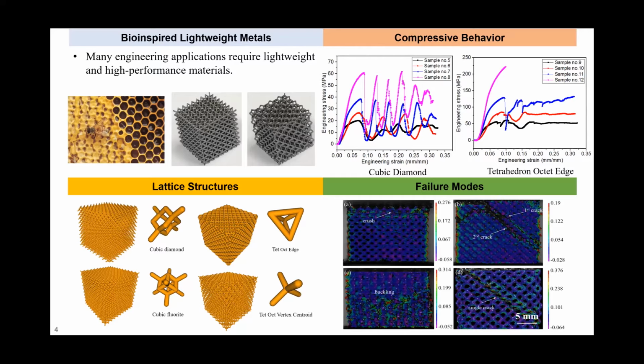These structures are inspired by honeycombs and also by crystal structures in chemistry. And these are only 2 out of 24 lattice structures we printed. These lattice structures are made of aluminum alloy and magnesium alloys. The reason why we selected aluminum and magnesium alloys is because the density of these 2 alloys is very low already. And then we further optimize the structure itself in order to further reduce the weight and also increase the strength to weight ratio. For this particular project, we're interested in the compressive behavior or compressive strength of these different materials or lattice structures.